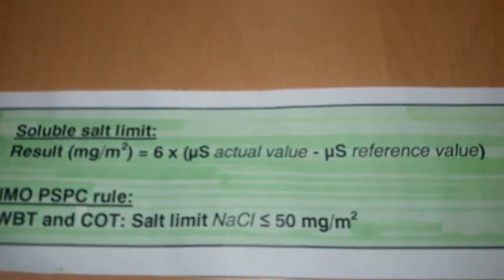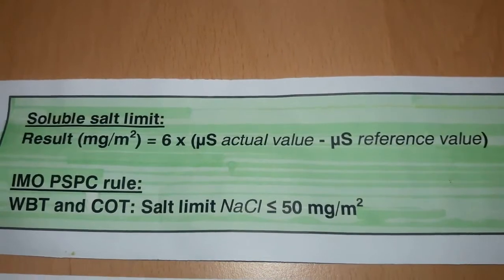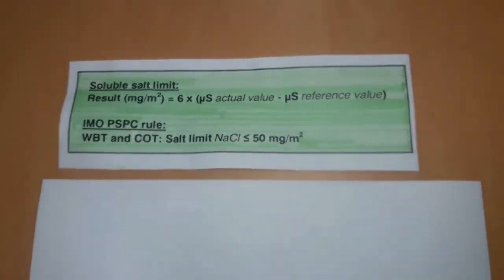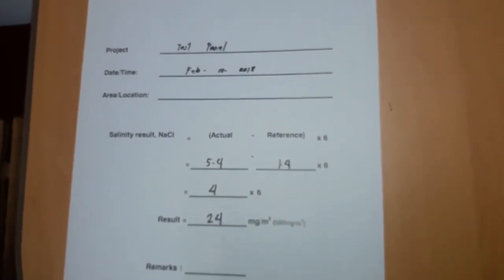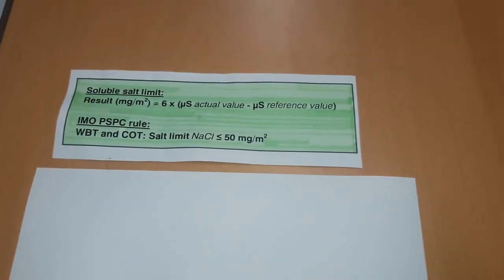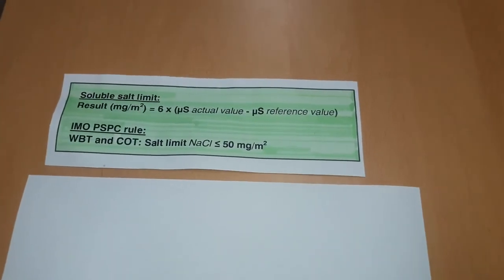Record and document the tested surface area. Indicate the result, pass or fail, as per PSPC rule. For water ballast tank and COT, the water-soluble salt limit is equivalent to less than or equal to 50 mg per square meter of sodium chloride.